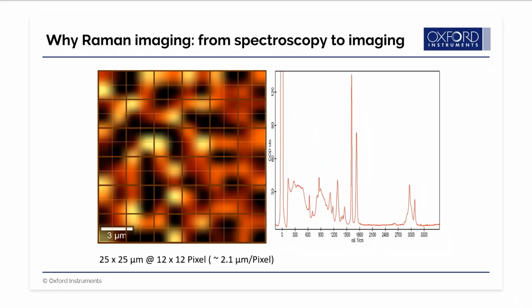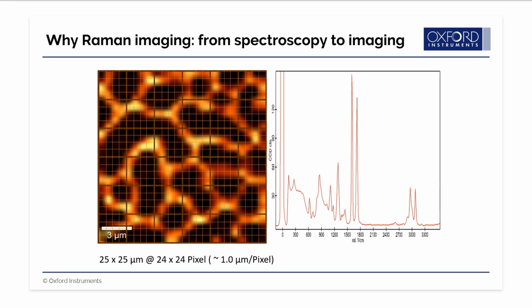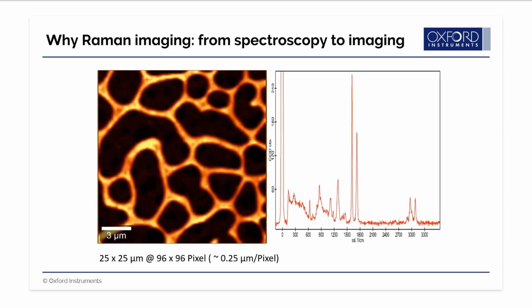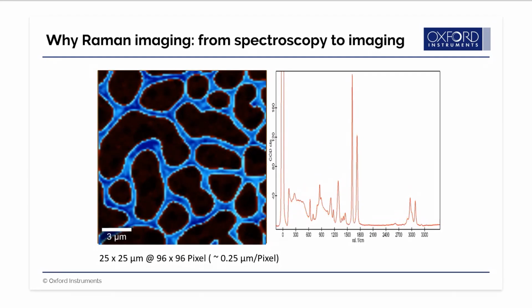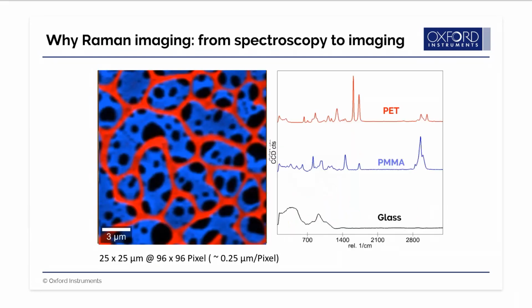The image shows more details and of course the signal to noise in the individual Raman spectra decreases. We further increase the number of pixels and decrease the integration time, and the image becomes better and better and better. However, the signal to noise in the Raman spectrum decreases. By a smart averaging of the spectra, however, we are able to reconstruct the low signal to noise spectrum of PET. The final image then looks like this with the corresponding color-coded Raman spectra.